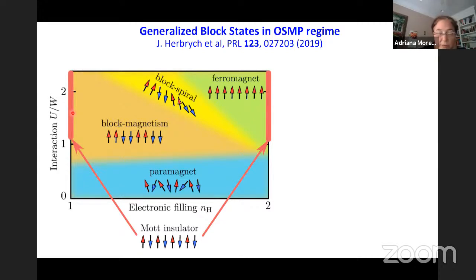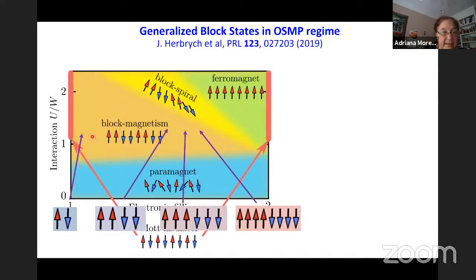But as we start doping, and U is relatively large, we go from the antiferromagnetic state to the block states. And you see we have blocks, but depending on the filling, as I showed you before, we have blocks of different size. In addition to that, we found a novel phase, which is this block spiral phase.